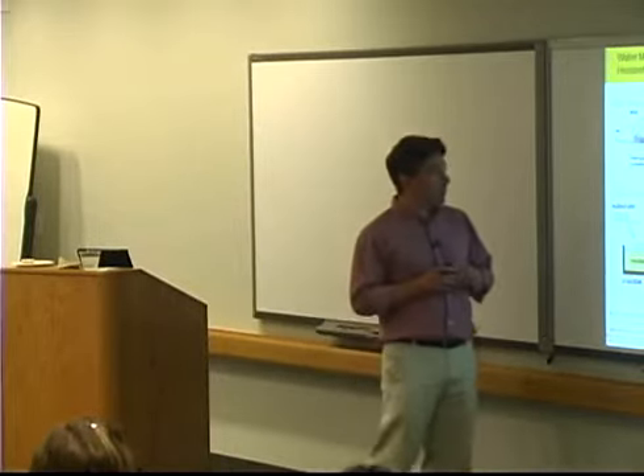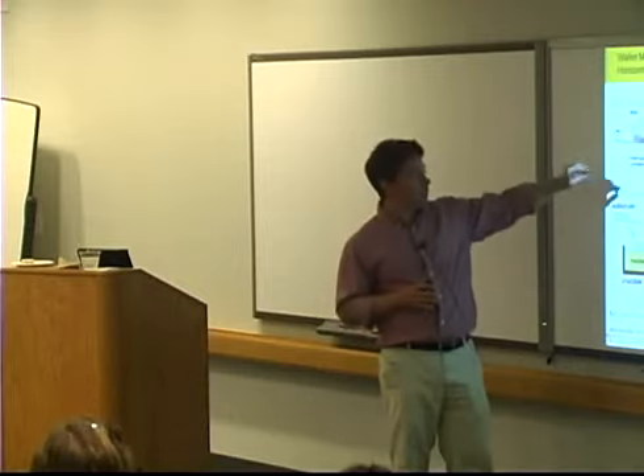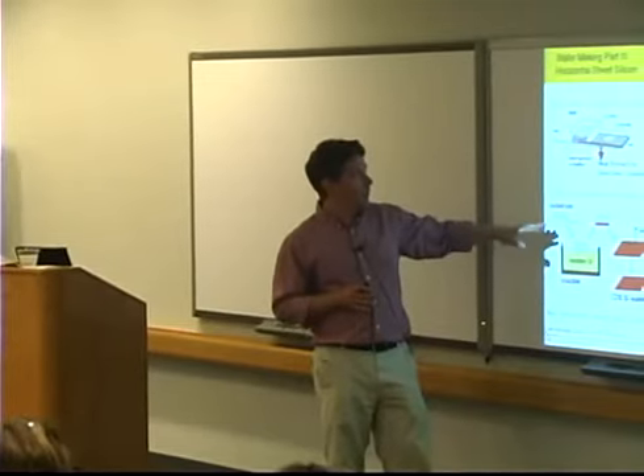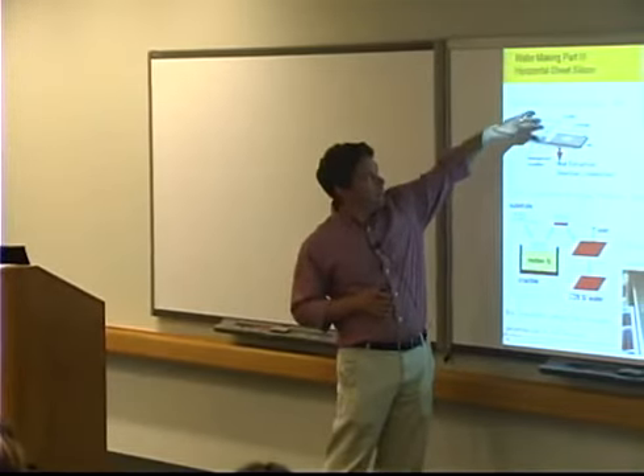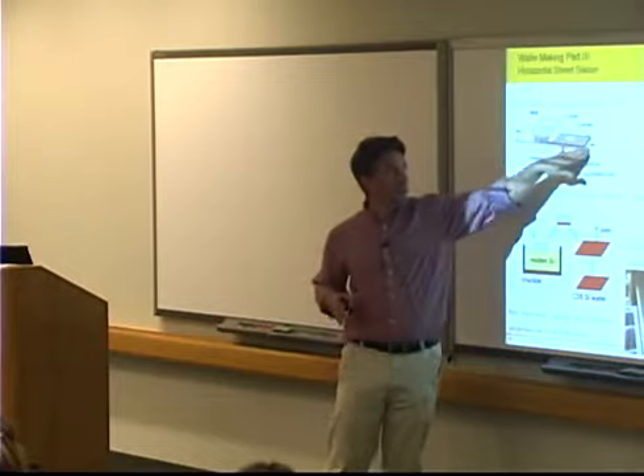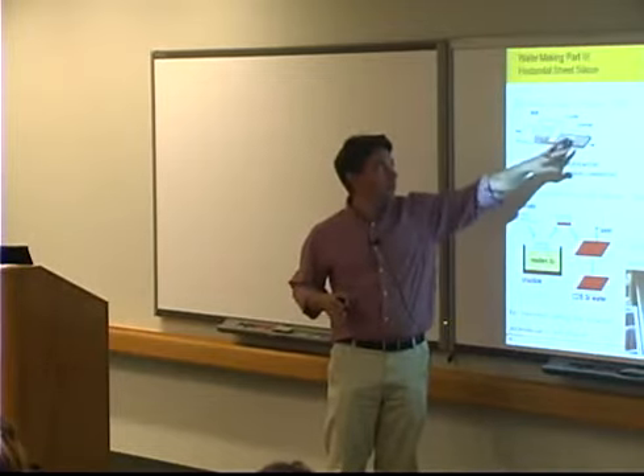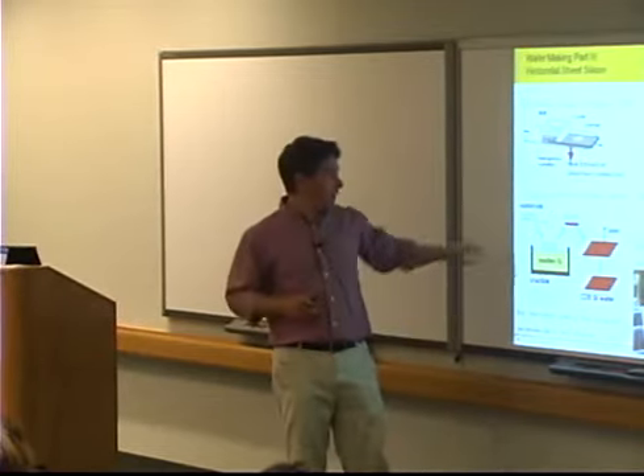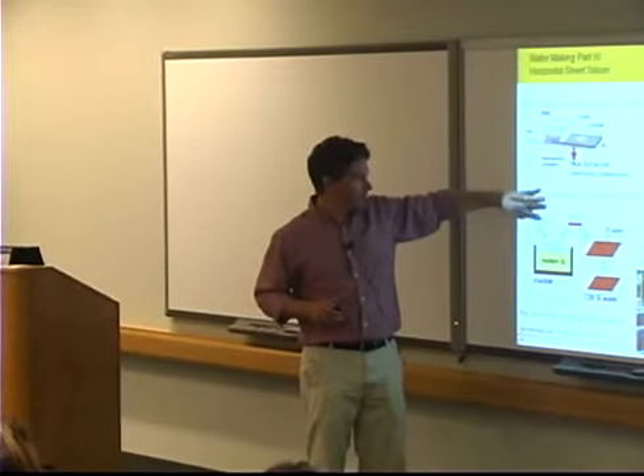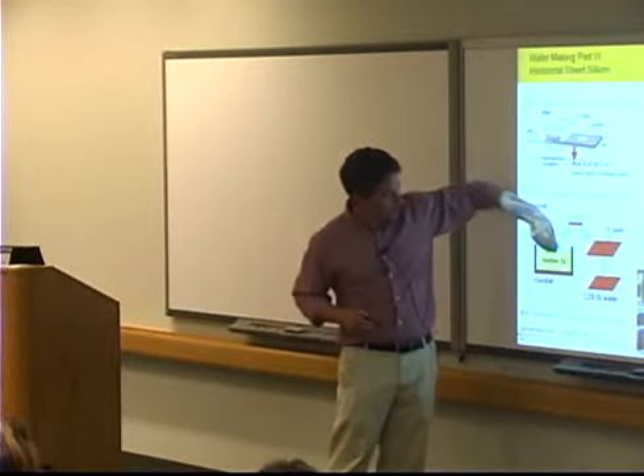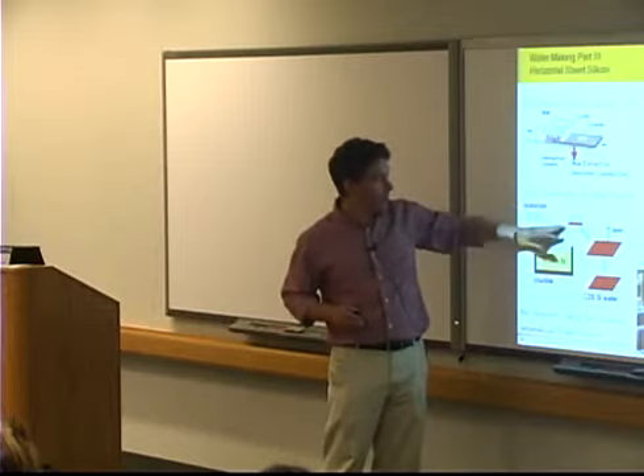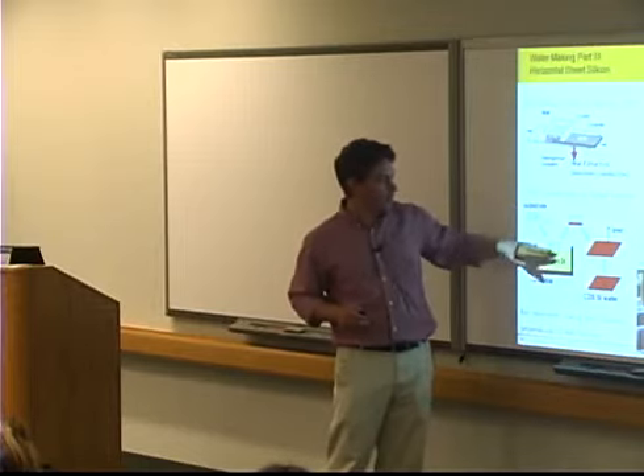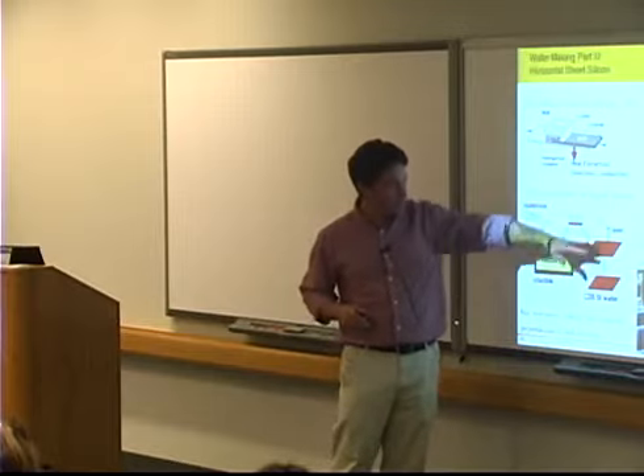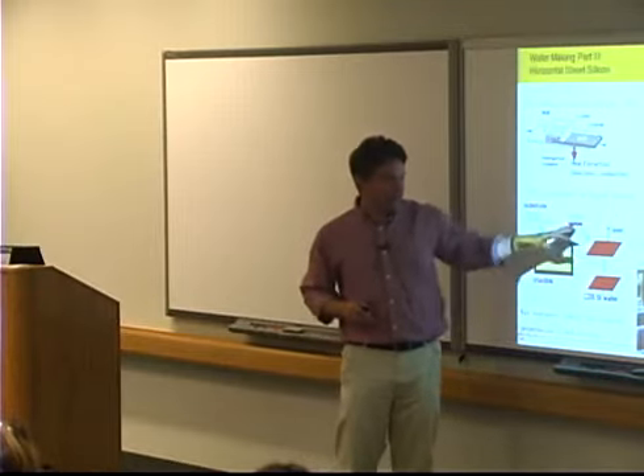So here's the last wafer making that we're going to talk about. And this is called horizontal sheet silicon. It's been tried 3 or 4 different times in slightly different ways. This one had this liquid on top here and the substrate kind of pulling out below it and freezing a solid sheet like that. This one here, this is a little broken, but it came down with things from the top that would try to solidify a sheet from the top and then pull it out and then release it. And the releasing is really the tricky part.